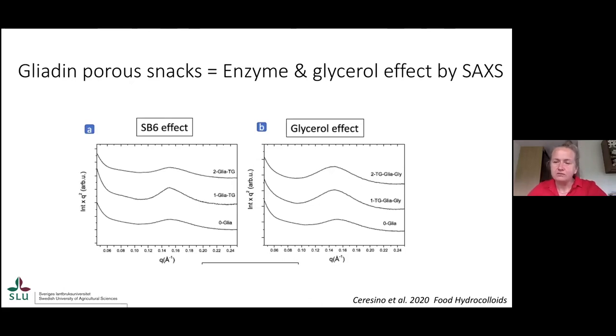And when we come to the scanning SAXS pattern, we also compare the enzyme effect. So SB6, this is a specific transglutaminase enzyme, is not commercial, it's an enzyme that we produced in the collaborators' lab. And we compared how the gliadins are impacted by enzyme concentration, the first graph. So there is a slight shift in the scattering pattern with the increase in the enzyme concentration. If you compare, while the glycerol is giving no effect, the glycerol together with the enzyme is introducing no structural changes. So the pattern looks rather similar, which means that the glycerol in some way is contributing to protein aggregation and not allowing the enzyme to perform its function.